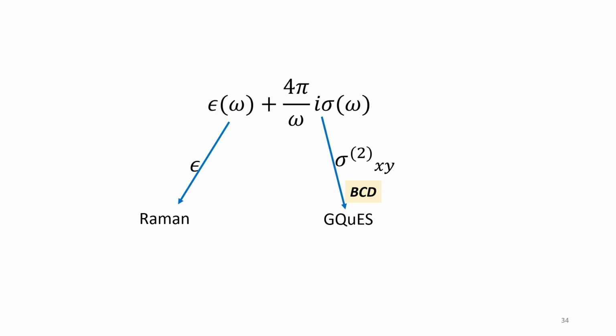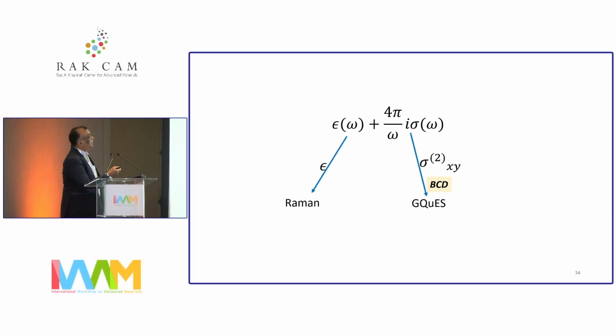So what is the take-home message? All of you know that the Raman spectrum is linked with the fact that the vibrational mode modulates the real part of the dielectric constant, which is governing propagation of light in a medium. But it also has an imaginary part, which is frequency-dependent conductivity. And what we show is that the off-diagonal part of conductivity, which is linked to the Berry curvature dipole, can be exploited to measure vibrational frequencies. And that's the spectroscopic technique that we have proposed using this analysis.